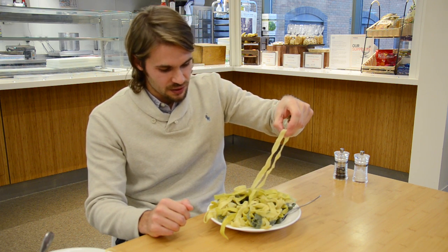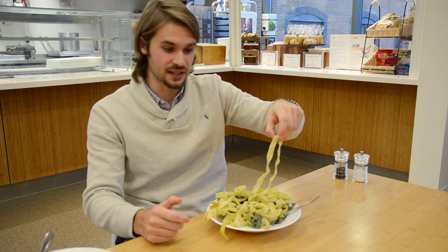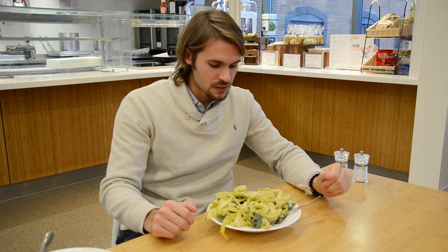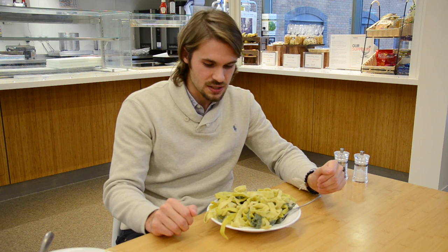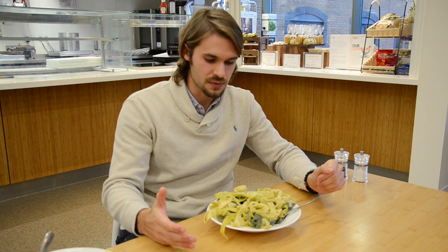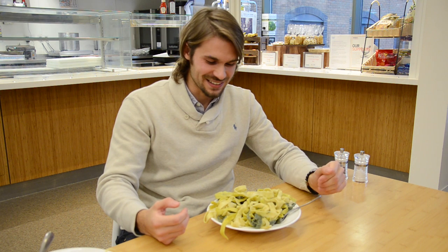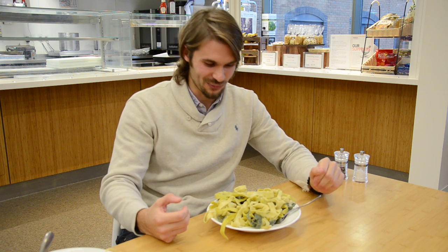If I try to pull one free, I realize I can't unless I pull other rings with it. This property is peculiar to the fact that these polymers are closed — they are rings. This type of interaction, which we call threading, causes the system to slow down a lot, and it becomes almost like a glass, which means it takes exponentially long time to move. This is why eating this bowl of pasta one strand at a time would take a very long time.